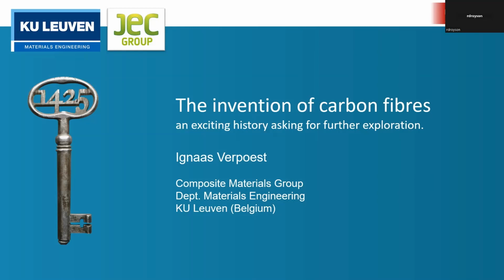But because you don't have this stretching during the oxidation, you will not have a very well oriented graphitic structure. And whether that is then isotropic or not, I do not know. But it will certainly be much less anisotropic, much less oriented than what we have now after the straining, the stretching of the PAN fibers during the oxidation step.